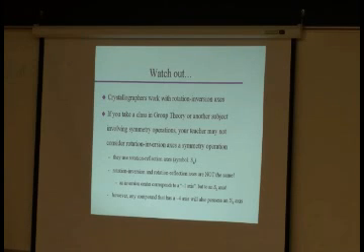Why is this important? Well, if you use rotation inversion and you look at a simple inversion center, that would be a 1 bar for us, okay? You do full rotation followed by an inversion, or you can leave the rotation out, obviously, right? So that's a 1 bar for us. In group theory, an inversion center is an S2, right? You rotate by 180 and reflect through the plane. So that's different, okay? An inversion center is not a 2 bar. The 2 bar, as a matter of fact, is a mirror plane. Because you rotate by 1/2, you invert, you end up right below the first object. So 2 bar is a mirror plane, while an S2 would be an inversion center, and an S1 would be a mirror plane. So watch it, they are not the same symmetry operations.